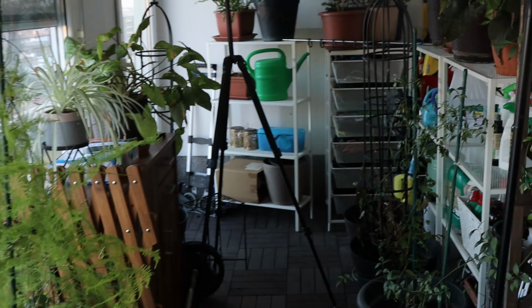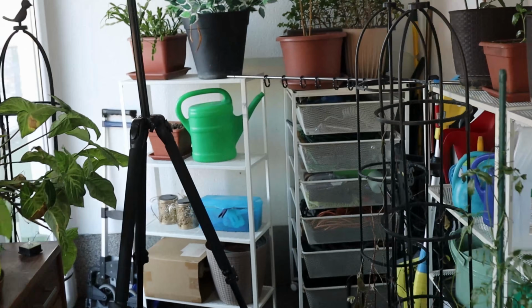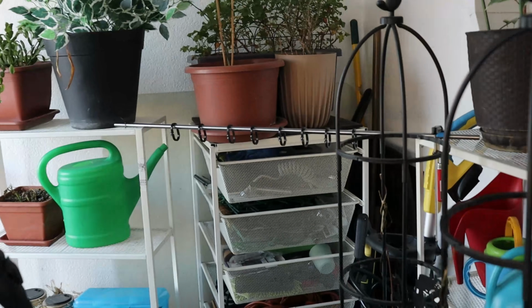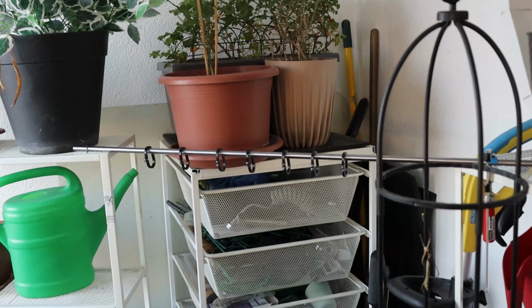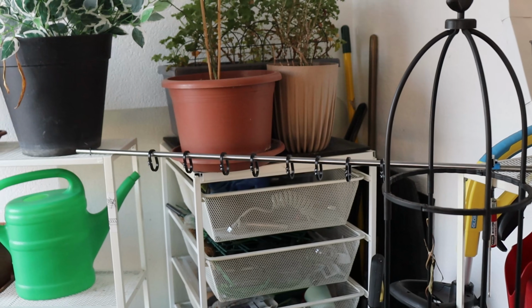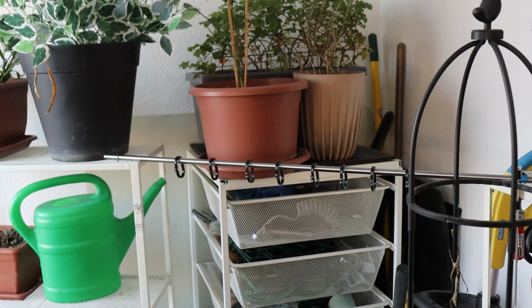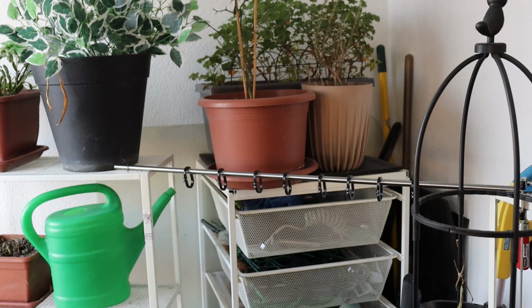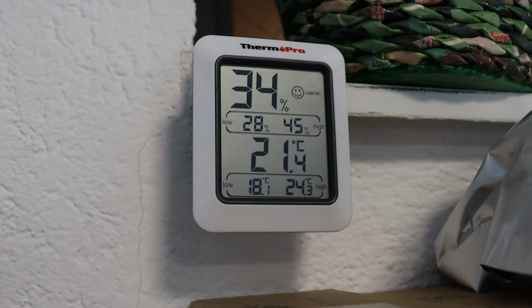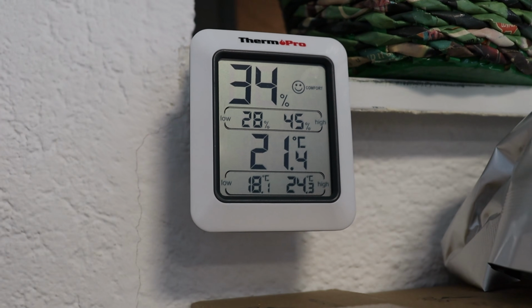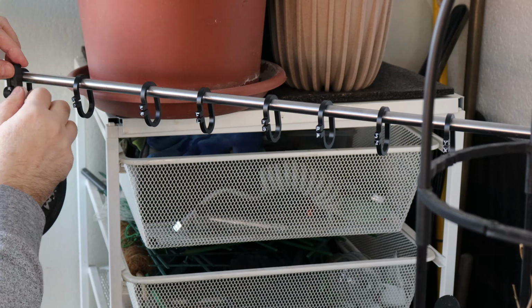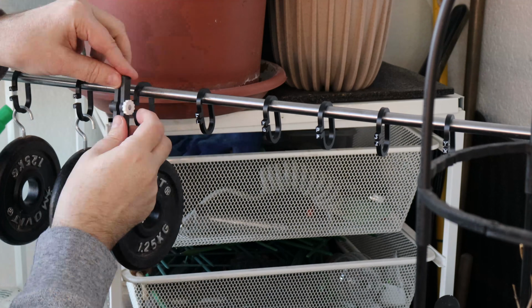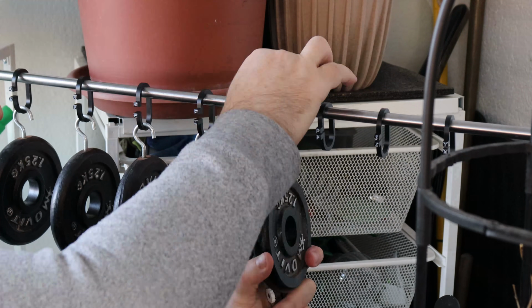In this small corner in our winter garden, I got the permission from my wife that I can place here my test objects and they can stay here 1 week. And I will not measure them every day, only now initial deformation and after 1 week. As you can see, typical temperature here is around 20 degrees Celsius. Creeping is a deformation under constant load, in this case 1.25 kilograms.